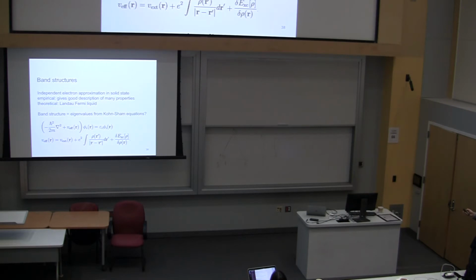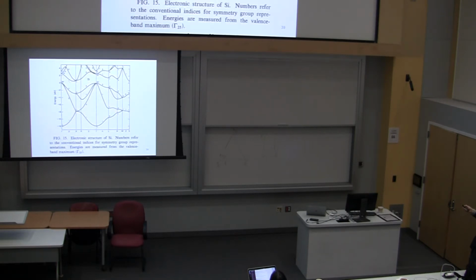So you have the one electron calculations. You get band structures that look pretty much like real band structures, except they're not quite right in general if you compare them with ARPES or something. The band gaps are often off by a factor of 2. The bandwidths are also off by some percentage. But if you just look from far away, it looks great.